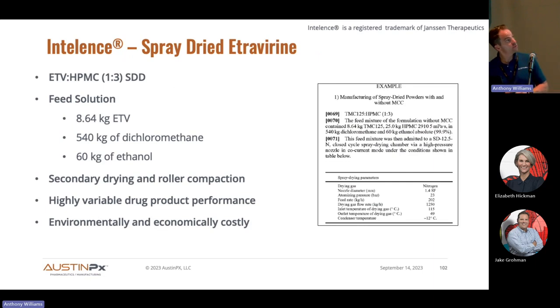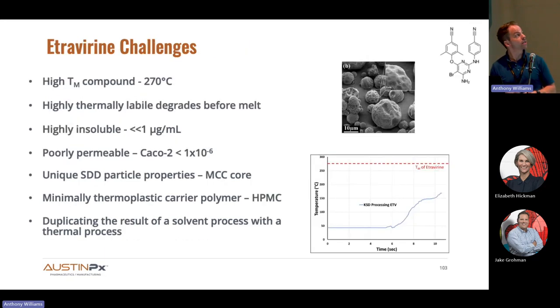A little more detail, specifically, it's a 25% drug load SDD. The thing to point out here is the feed solution has a relatively low solids load. You know, you're spray drying, per this patent example, 600 kilos of solvent, a majority of that chlorinated solvent, to obtain less than 9 kilos equivalent of etravirine. So that's a problem, I think, in terms of the way we see green chemistry now and the ecological footprint. Like most spray dried products, it requires secondary drying and roller compaction. I've already mentioned that the drug product has highly variable performance, and obviously it's environmentally and economically very costly.